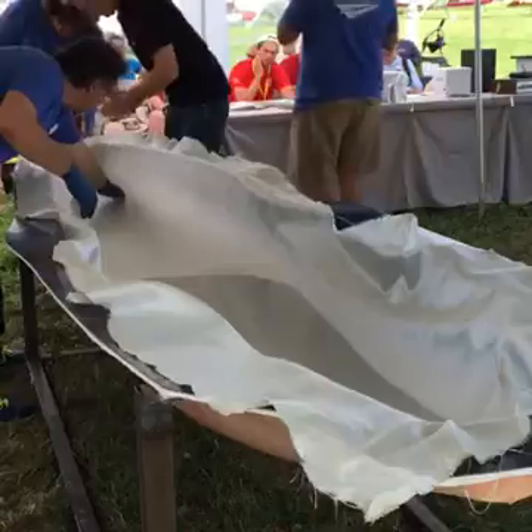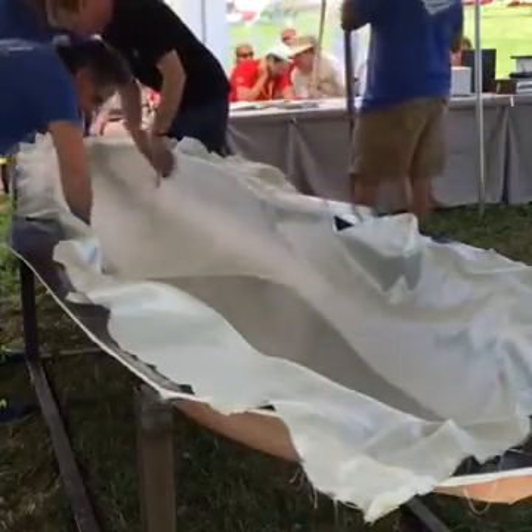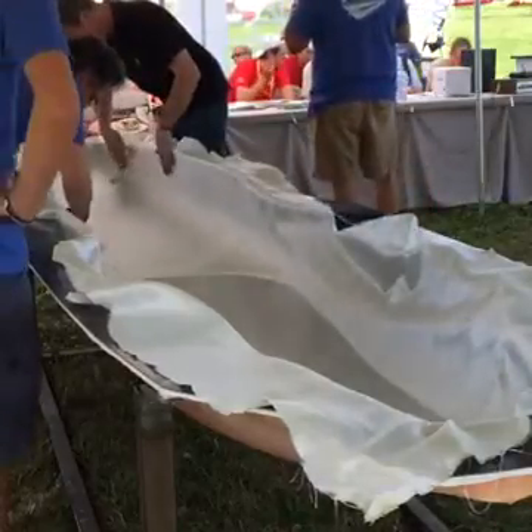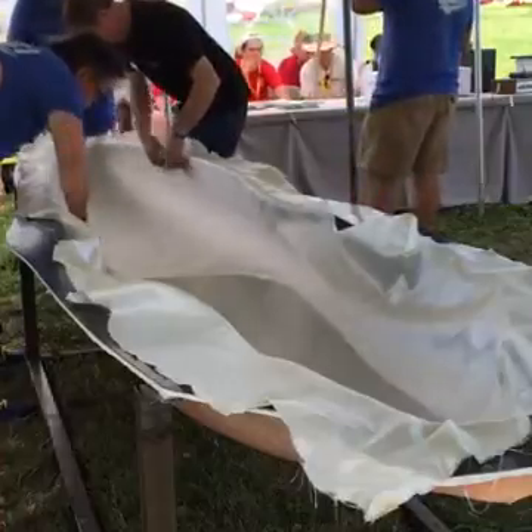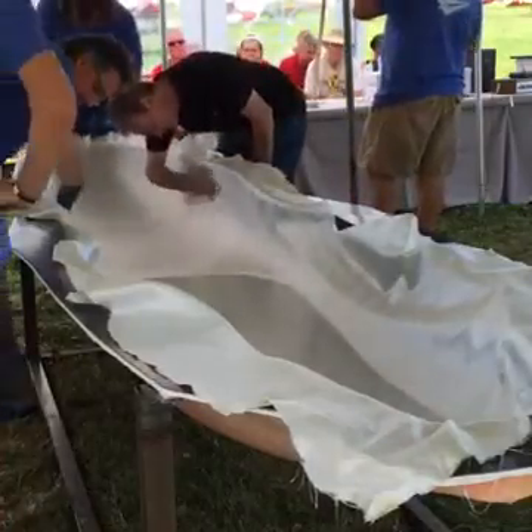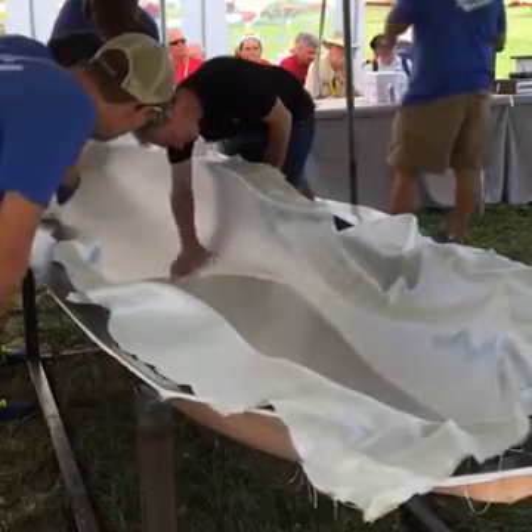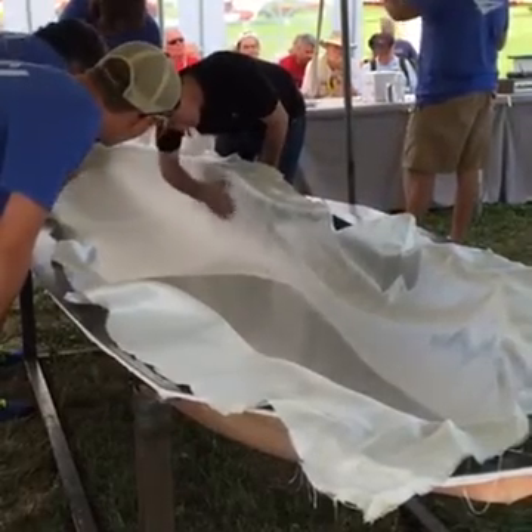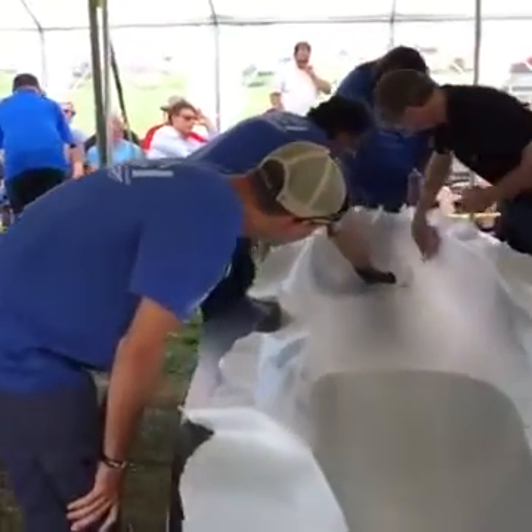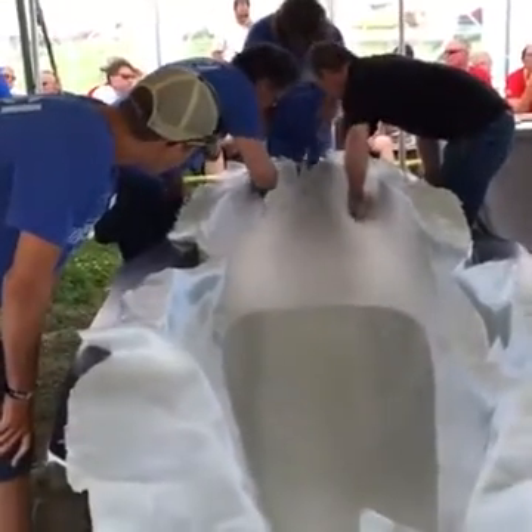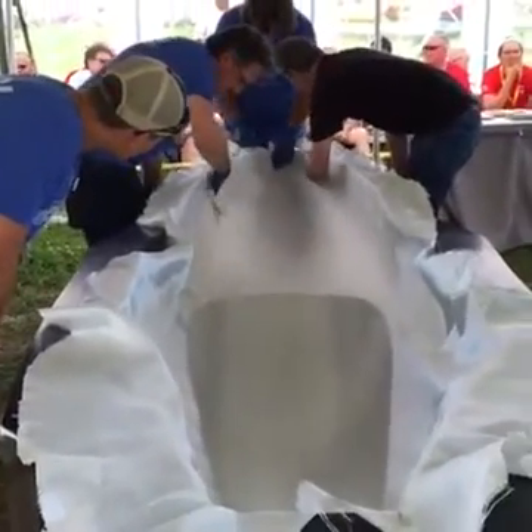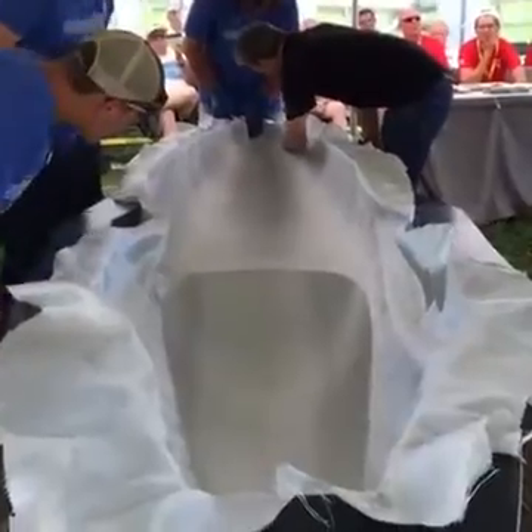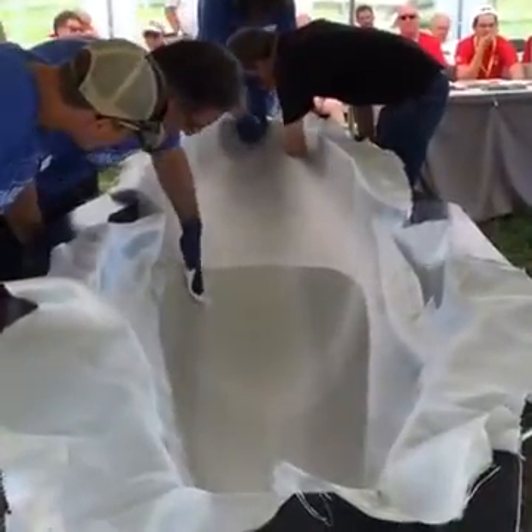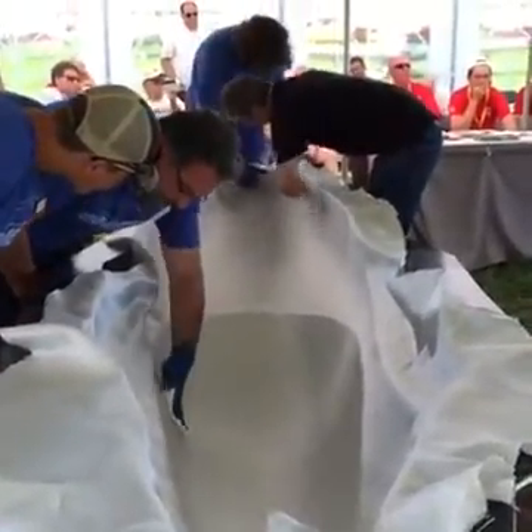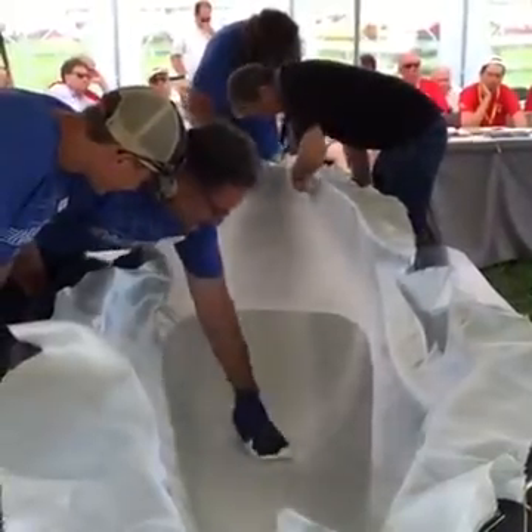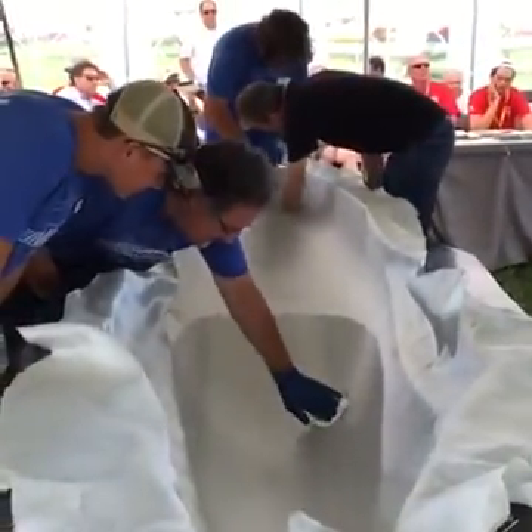So the question was, epoxies are pretty ratio sensitive. This resin is ratio sensitive as well. Let me expand on that just a little bit. Epoxies, not only are they ratio sensitive, but they're also amine sensitive. You can get different properties. What's cool about epoxies, and I was an epoxy chemist for 10 years, is you can use different amines for the same epoxy and get totally different results. You get better moisture absorption, you get better infusion. Whatever the properties were you were looking for, you could change out the amine and get that.